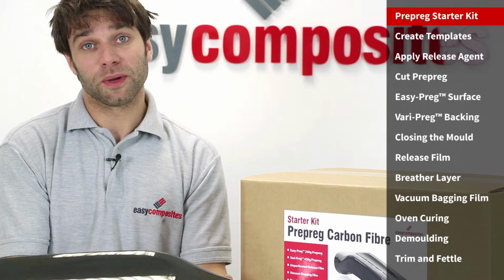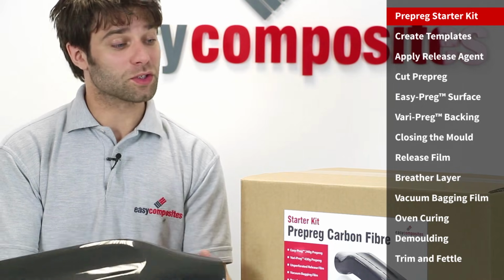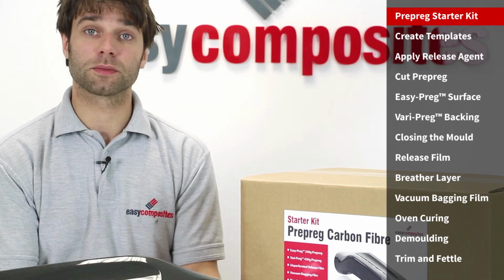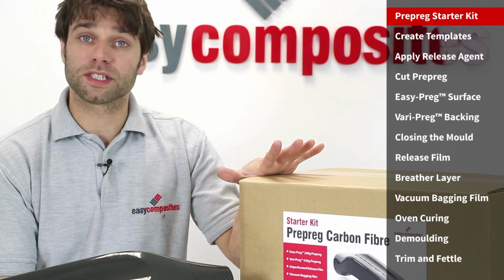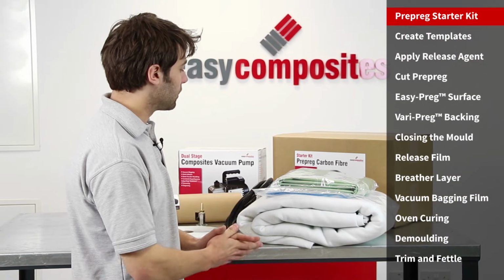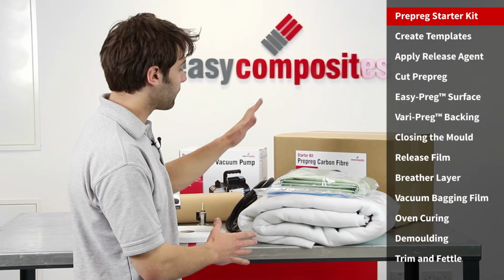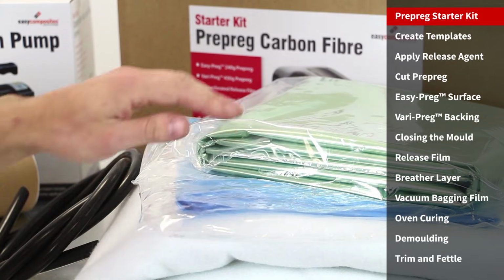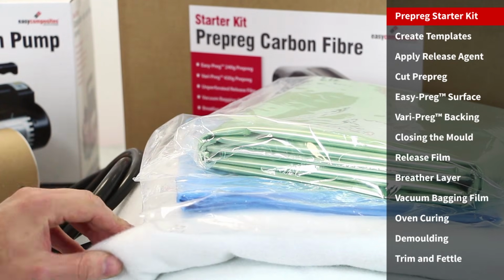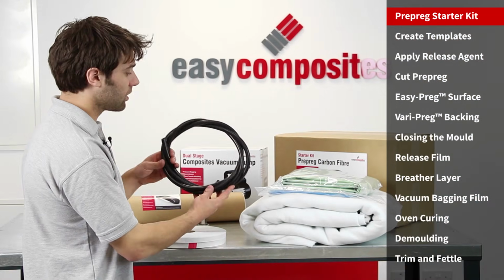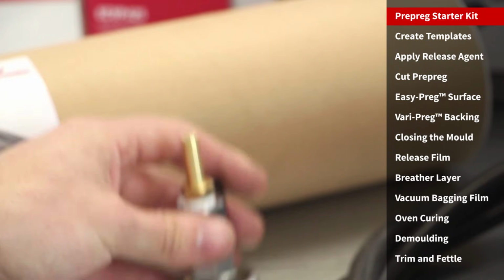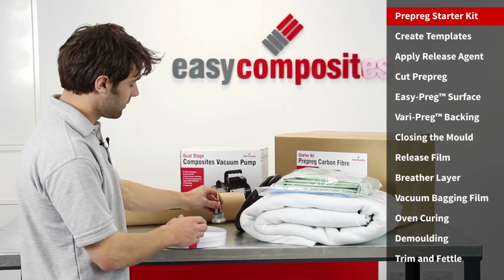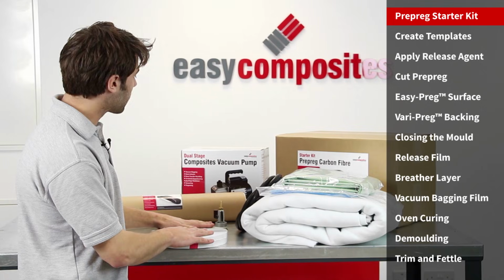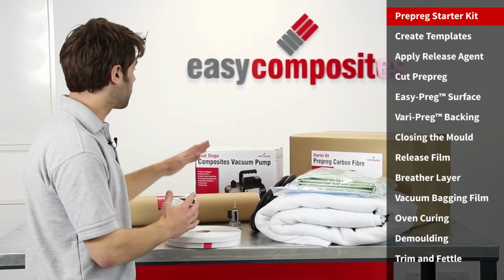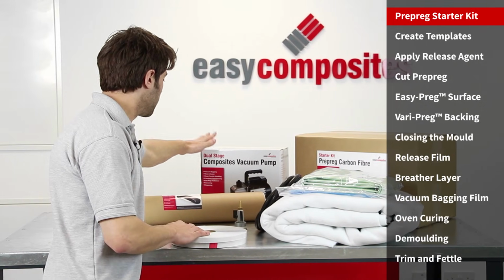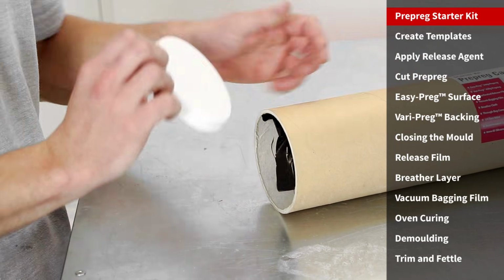For what we're doing today, we can keep things really simple because almost everything that we're using to produce this part comes in our Pre-preg carbon fibre starter kit. In the kit, you've got all of the consumables that you need. You have 5 metres of vacuum bagging film, unperforated release film and breather cloth. You also get a high temperature silicone vacuum hose, through bag connector, 2 rolls of vacuum bagging gum tape, and optionally, if you don't already have a pump, a Composites vacuum pump. Then, of course, the Pre-preg itself.